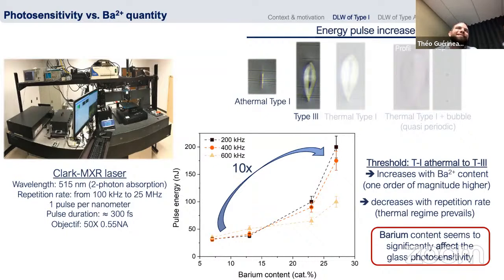Okay. I would say that in this case, when you increase the barium content, you extend much more the range in which you can inscribe some modification. So at low barium content, you see that the threshold to the type 3 is kind of low considering the pulse energy, but also the window in which you can work to perform the thermal type 1 is very reduced. It is much more than an order of magnitude difference if we talk about only the window for the thermal type 1.